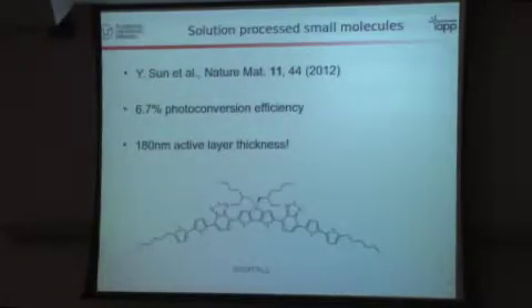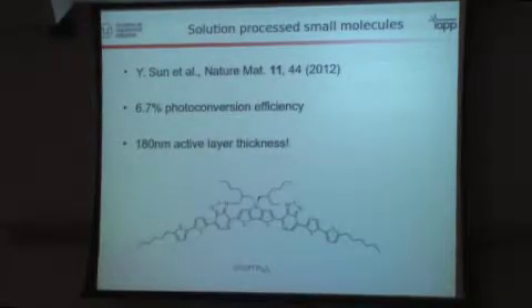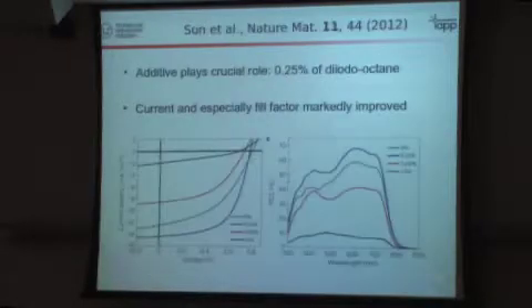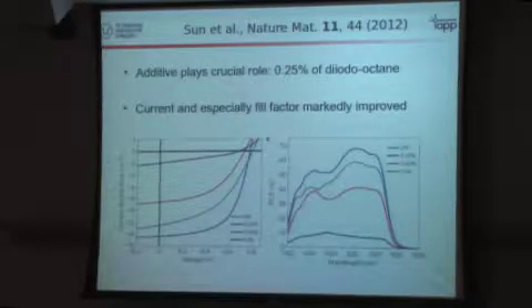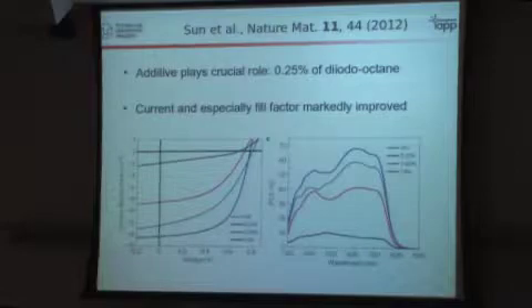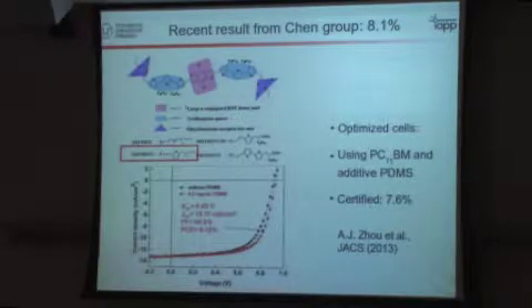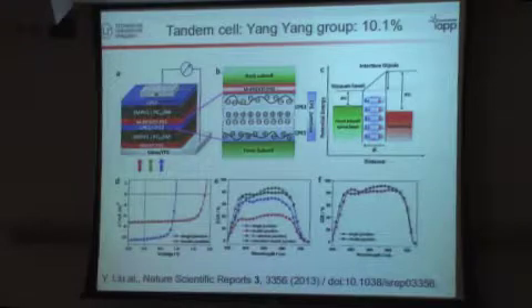Again, in the small molecule field, people have used either solution processing or evaporation, and solution processing has some advantages here, like you can make fairly thick active layers. As you'll see, in my experience they are much thinner, because you can make good transport properties. Especially the results from the Sun group showed that by adding an additive, you can control the morphology, and by using a suitable concentration of additive, the morphology is much better and the cells are much better. And there are some recent results. I found a result with more than 8% now using PC71BM. And the most recent result is now from Nature, from the Yang group, which had a tandem cell at 10%. So for the polymers, the numbers are quite good and almost as good as for the small molecules.